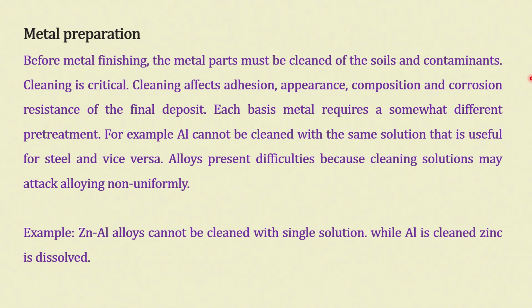So, each basic metal requires a somewhat different treatment. We cannot have a uniform pre-treatment for all the metals, that is not possible. For example, aluminum. What happens to aluminum? Aluminum cannot be cleaned with the same solution that is useful for steel and vice versa. Many of the metals we clean with sodium hydroxide. Now, aluminum cannot be cleaned with sodium hydroxide at all, because sodium hydroxide will dissolve aluminum. A very simple reaction, NaOH plus Al will give you NaAlO2. So, that will go into solution.